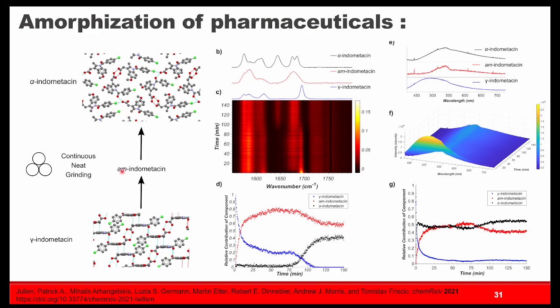And amorphous phases are really tricky. The reason is that they're inherently thermodynamically unstable, and so they tend to relax to different phases. And so we can start looking at this in ball milling reactions. And we think amorphous phases play a really significant role in milling processes, but it's really hard to look at because they're not crystalline. And so you can't use diffraction-based techniques to really get very much information about them. And so we turn to spectroscopy. And in this case, we can actually use Raman spectroscopy as well as fluorescence to look at this transformation.